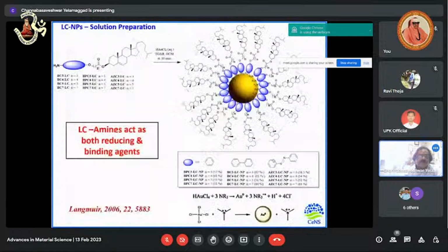See, this is what we have done. What we have taken is amines, and we have used auric chloride, Au3+ ions. Here, the amine, the liquid crystal ligand, not only acts as a reducing agent, but also gets attached to the central gold scaffold. It's very clear that the liquid crystal ligands, which you use as amines, not only reduce Au3+ to Au0, but also get attached to the central gold scaffold. This is the mechanism by which the primary amine reduces Au3+ to Au0.